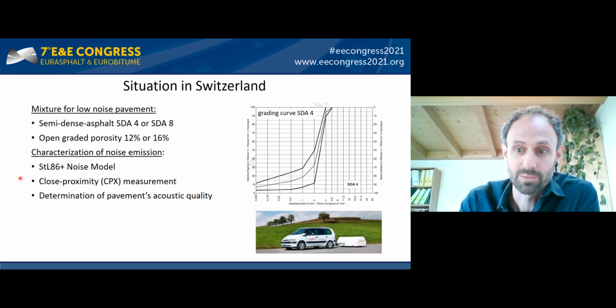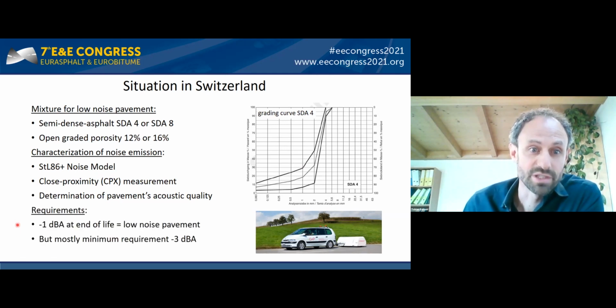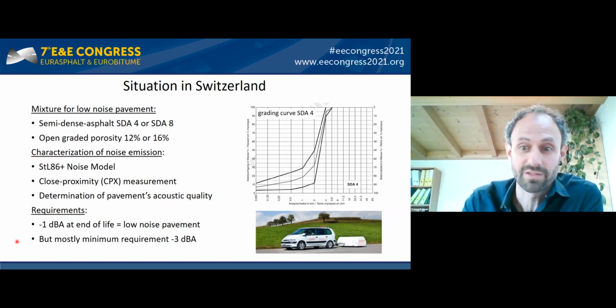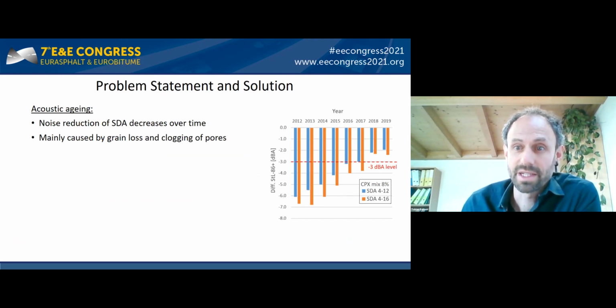The values are always expressed in minus decibel compared to the model. If, for example, a road has -1 decibel at the end of its lifetime, it's considered a low noise pavement. But in most cases, a minimum of -3 decibel at end of lifetime is required. The intention of SDA mix design was to use small grain with small pores that would provide acoustic favorable surface texture. It was also believed that the tiny hydrophobic pores would be prevented from clogging over time. Unfortunately, reality is a little bit worse. In this plot on the right, you see the course of acoustic aging of two roads, SDA4 with 12 and 16 voids in comparison.